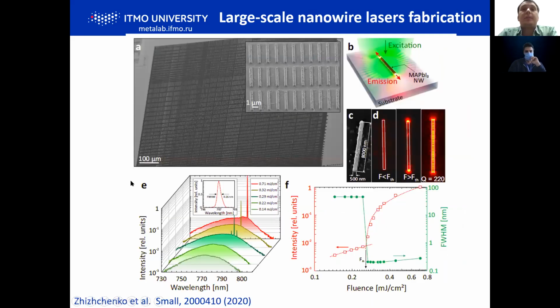And by shaping the beam in another way, we can create stripes of intensity, and then remove the material from the film, and the remaining forms are nanowires. So by laser ablation, we can also create huge arrays of nanowire lasers, which are really sub-wavelength. And again, this is due to the low thermal conductivity and high robustness of perovskites to overheating. Therefore, we can still have high quality lasers even with sub-wavelength dimensions.